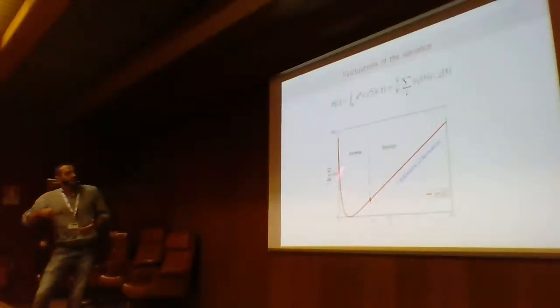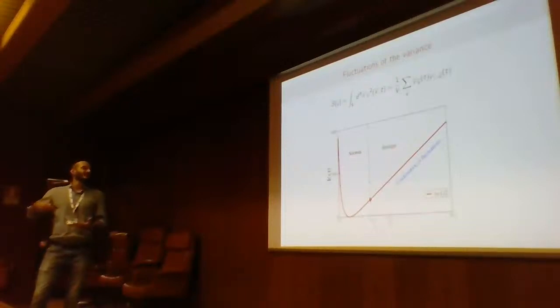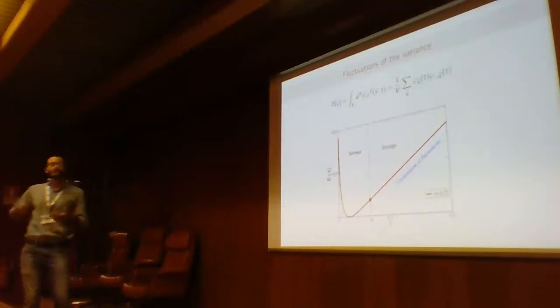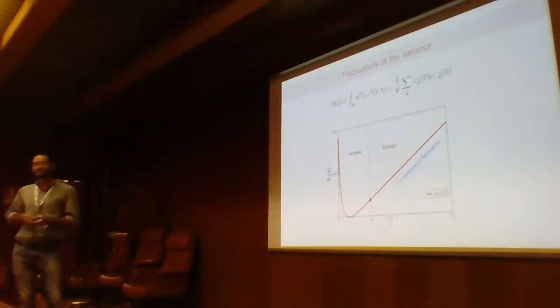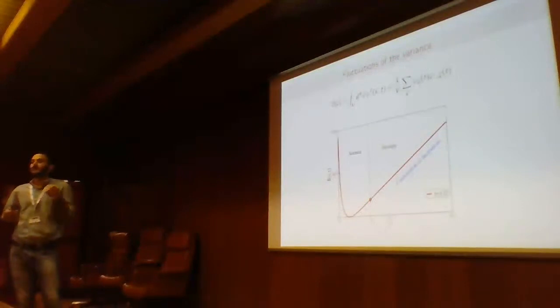I have two regions, one which I call normal, and one which I call strange. And at this point, the critical point, there are discontinuities in the derivatives, and it becomes linear here. And I call this condensation of fluctuations because for all the values of the observable when it fluctuates in this region, the microstates of the system are particular.